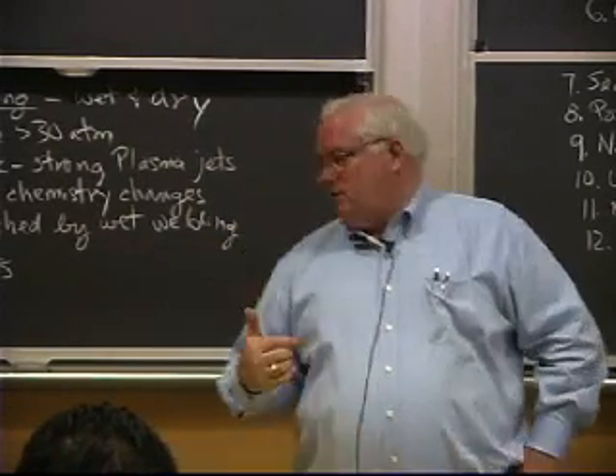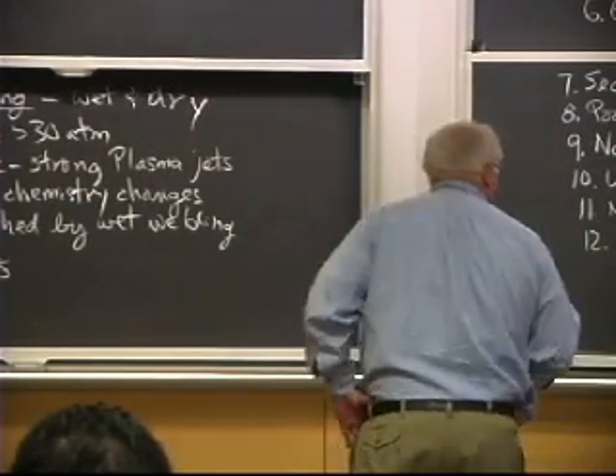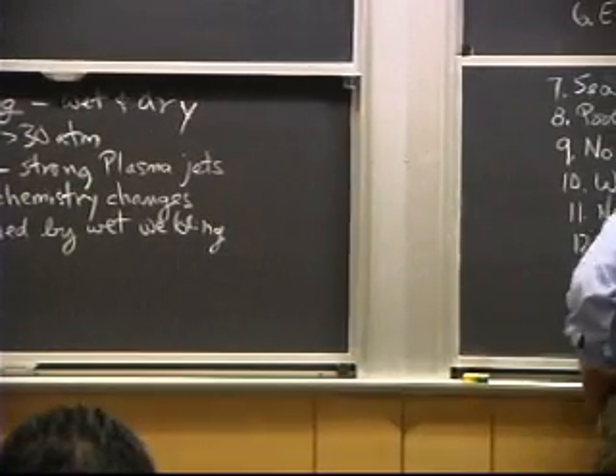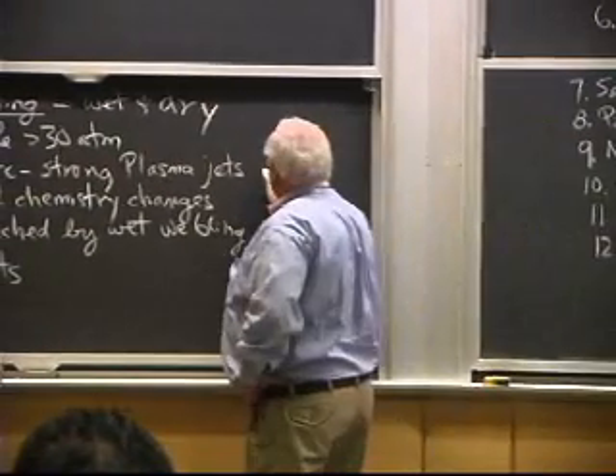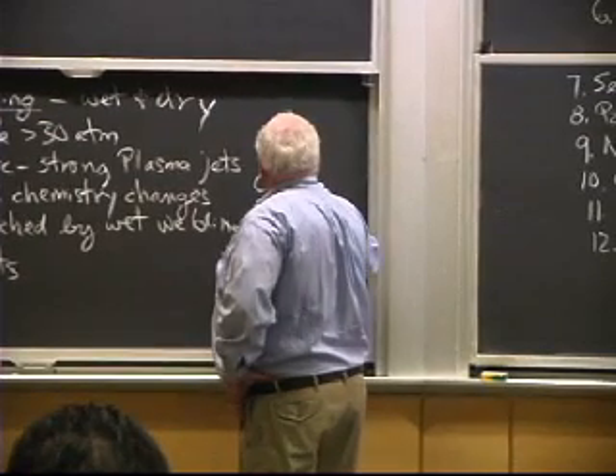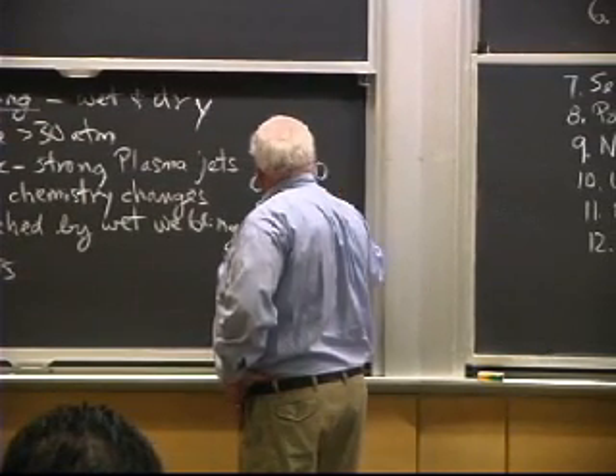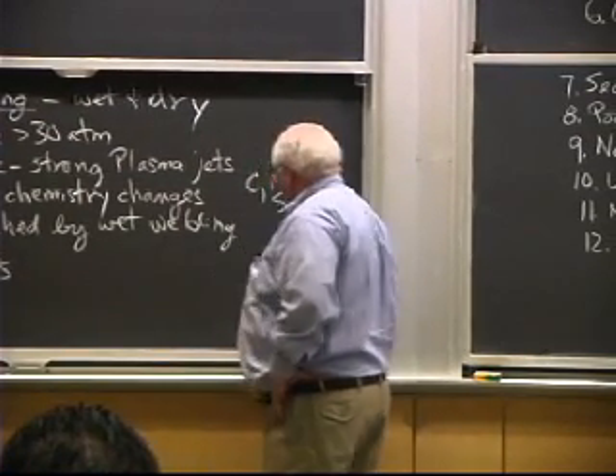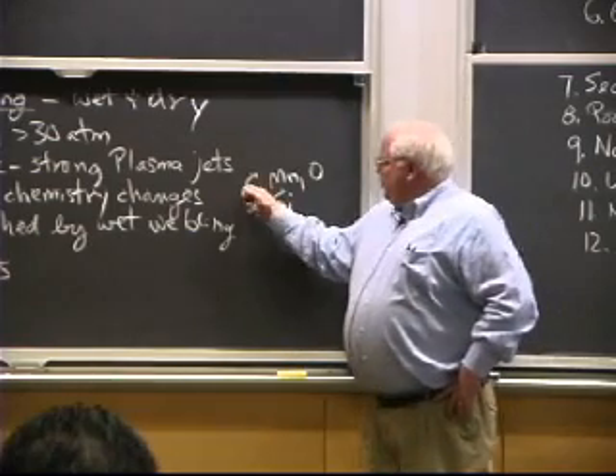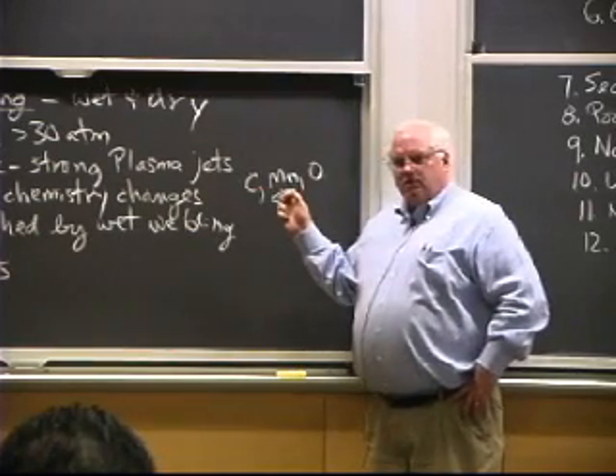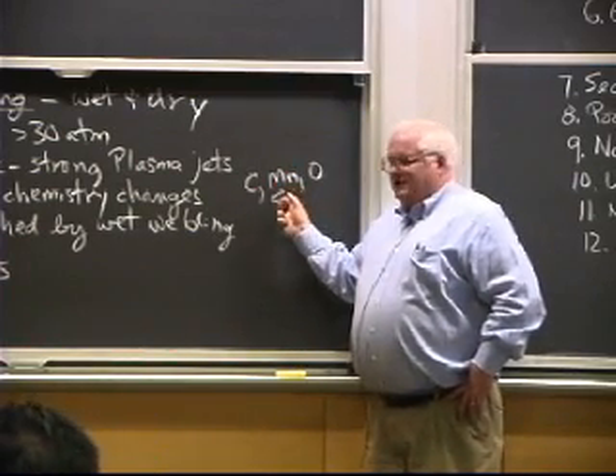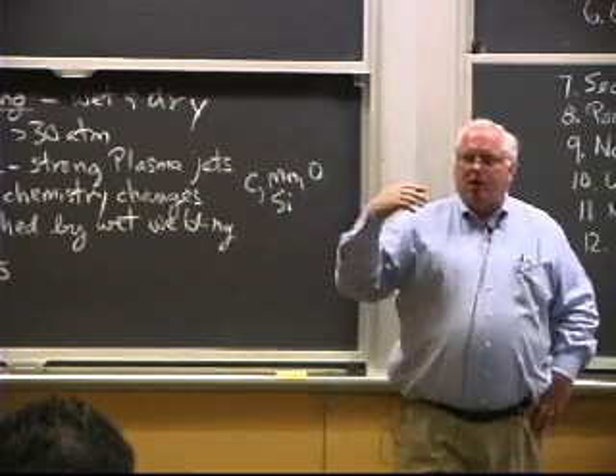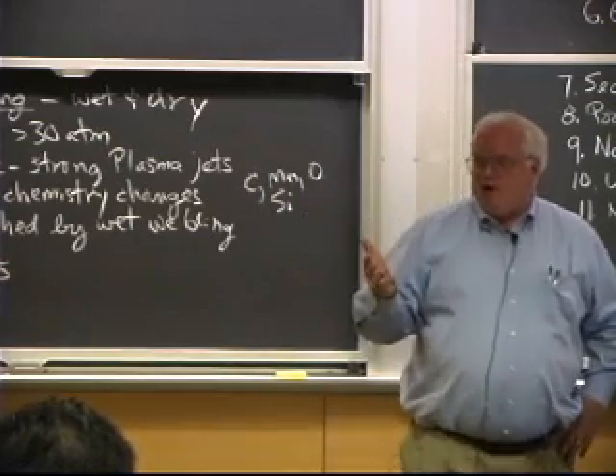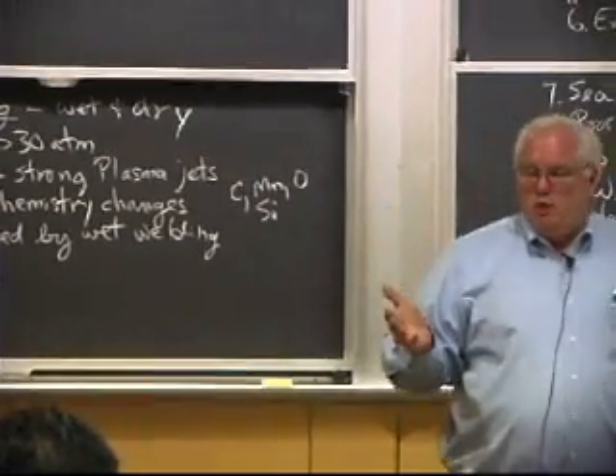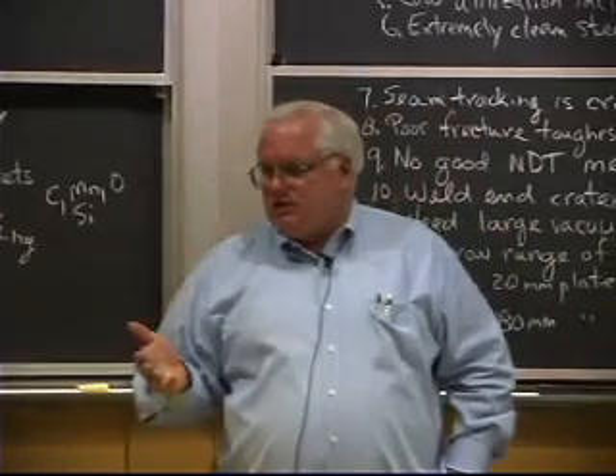It turns out if you look at typical weld metals, you've got to worry about carbon, manganese, oxygen, silicon. As it is, we formulate special electrodes with different amounts of manganese and silicon depending on whether we're welding with argon shielding when we're doing gas metal arc, or whether we're welding with 100% CO2.